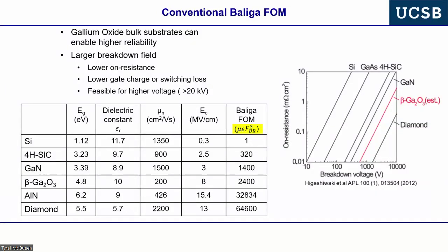And everything is referenced here to silicon. And so the mobility matters, the dielectric constant matters, but what really matters is the breakdown strength, and this goes as the cube of the breakdown strength. And so if you throw these numbers here, here, here into this FOM and then normalize it to silicon, because this will have dimensions, but everything's normalized to silicon, okay, you'll find that ultra wide bandgap semiconductors for the drift regions, for the on-state, minimum resistance, and the ability to hold off-state voltage look extremely favorable. I mean, 3 orders of magnitude, almost 4 orders of magnitude better than silicon, okay?